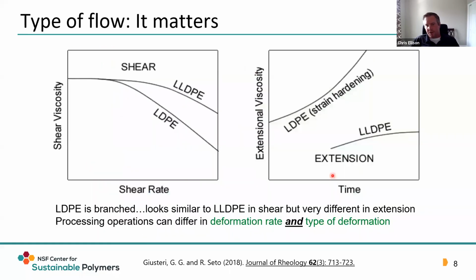So rate of flow matters substantially. The type of flow is also quite important. Here I'm showing the shear viscosity and the extensional viscosity, comparing low density polyethylene to linear low density polyethylene. You can see that the shear viscosity of those 2 systems looks relatively similar. They both shear thin, and they're not that different. However, if you look at the extensional viscosity, which is a different type of flow, the LLDPE doesn't exhibit much extensional strain hardening, while LDPE strain hardens substantially.